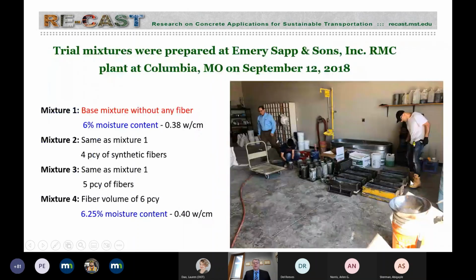We did quite a bit of testing using the equipment of the contractor and his sites. And as you can see here, this is Dr. Farzadnia, who was working with some graduate students in our team, made a lot of samples. We had 4 mixtures. The first one is a base mixture without any fibers. So the 0.38 water to binder ratio corresponds to about 6% moisture content. And this was again optimized using the modified Proctor test that I showed earlier, moisture content versus density.